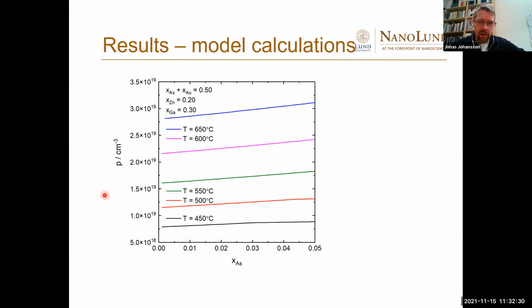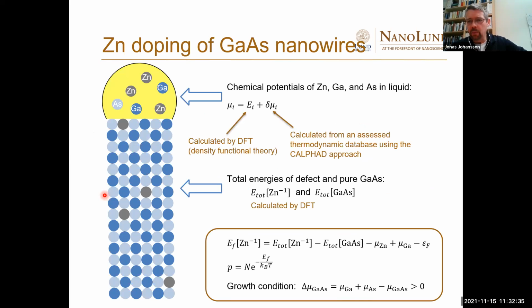This dopant incorporation model is the same that we use for bulk. Here, no kinetics is involved, no surface energies, nothing like this. This is only incorporation. The only thing specific to nanowires here is the chemical potentials and the mixture, noticing that we have gold and so on. But if in a kinetic model or a nucleation model we need surface energies, then yes, the dopant would influence the surface energies, definitely. And zinc also influences the chemical potentials of gallium and arsenic. But apart from that, there are no really nanowire specific aspects here. But surface energies, it would change, absolutely.